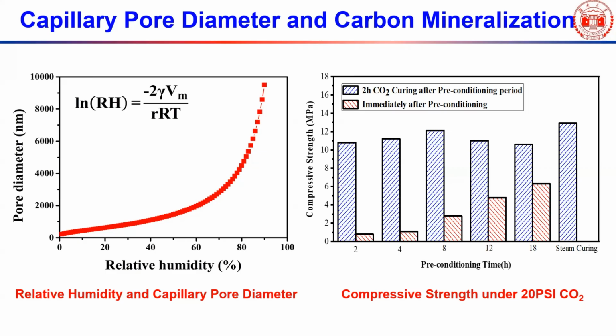With molecular dynamics, you can also calculate the surface layer thickness of water on a flat particle surface. But on the other hand, as I said, for different raw materials, or even different pore solutions, the surface tension, the gamma here, will also be different. So this means it's not just simple, I remove a certain amount of moisture through drying. Scientifically, you probably should really do more measurements, understanding the relationship between pore diameter and relative humidity, and then get a clear explanation of carbon mineralization. Okay, so this is it.